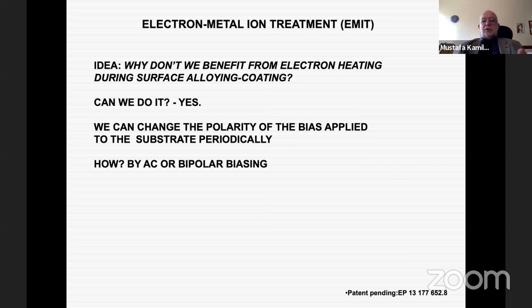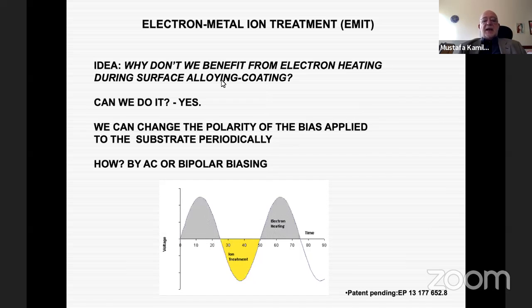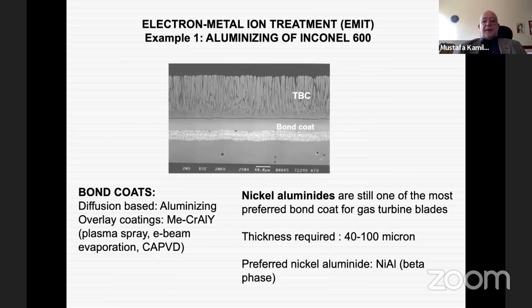So this is also a patented technology of our group that has been registered. So we started to use an AC bias voltage. When you apply an AC bias voltage, in the positive cycles of the AC bias, electrons come to the surface of the substrate. In the negative cycles, on the other hand, the ions in the plasma come to the surface and they deposit. So this was the idea that we started to apply.